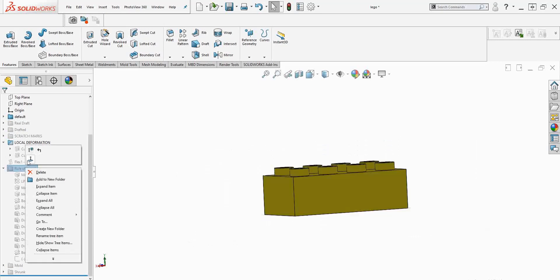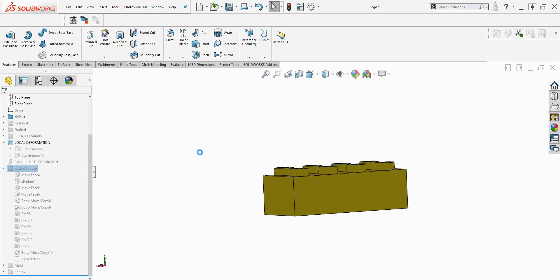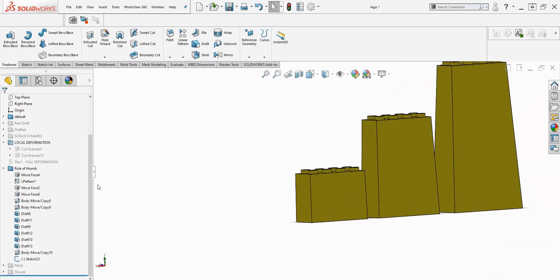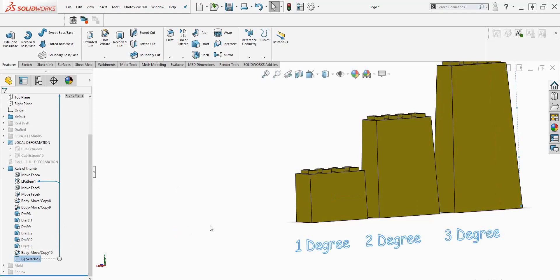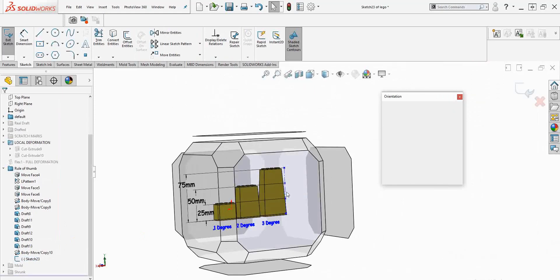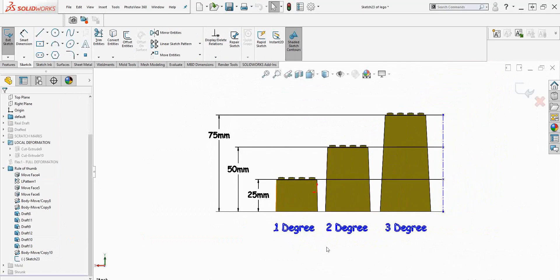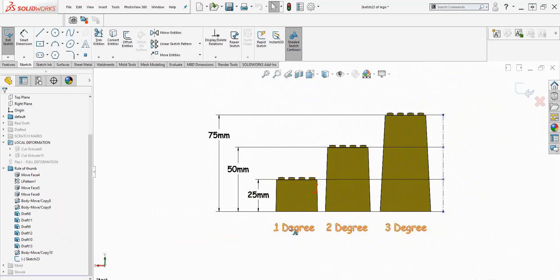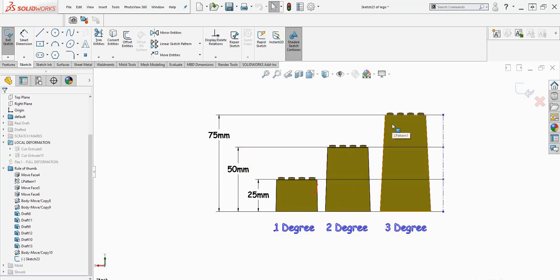So let's say that we have three Lego pieces and the first one is 25 mil tall, the second is 50 mil tall, the third is 75. You want to add one degree of draft every extra 25 millimeters. So the first 25 mil deep you need one degree of draft, the second 50 you need two degree of draft, the third 75 three and the fourth would be 100 mil and it would need four degrees of draft. So the height or the depth of the part is relevant to the allowable draft. So that is the general rule of thumb for that.